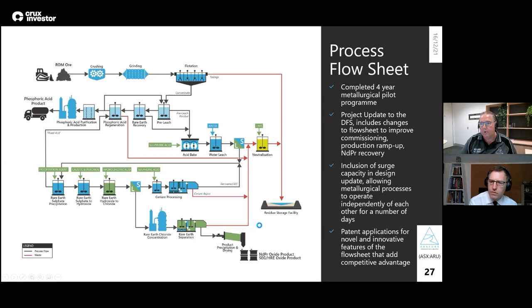Shall I put the flow sheet away now? Yes, thank you. So we've done about 4 years of piloting on the flow sheet, starting with about 15 to 20 tons of ore from Nolans, which we did through large diameter bore drilling. We then put it through every stage of this flow sheet. There were about seven stages right through, so we did it in various stages. We didn't go and build an integrated pilot plant. There was no real need for that.